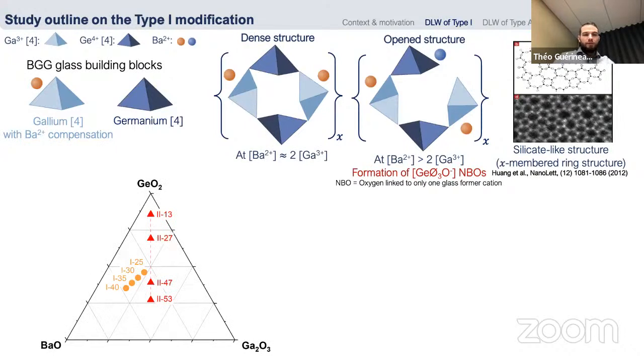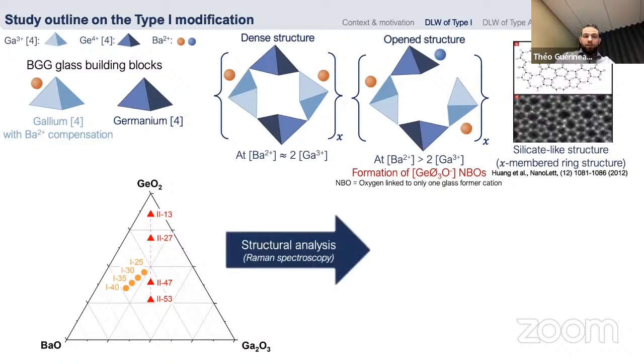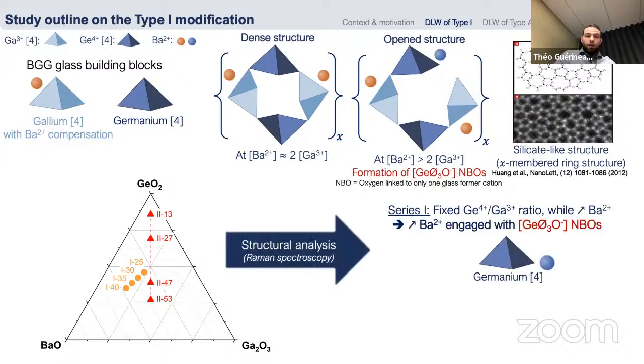So here is the ternary diagram of the BGG glasses composed of barium oxide, germanium oxide, and gallium oxide. We work in 2 series. Thanks to structural analysis performed by Raman spectroscopy, we observed that in series 1, when we fix the ratio between germanium and gallium while we increase the concentration of barium, we observe an increase of the barium engaged with the non-bridging oxygen of the germanium tetrahedra.